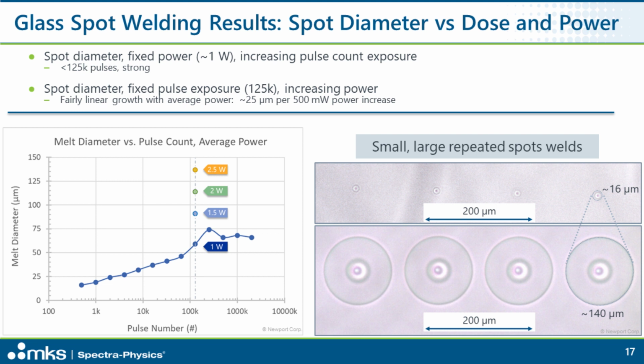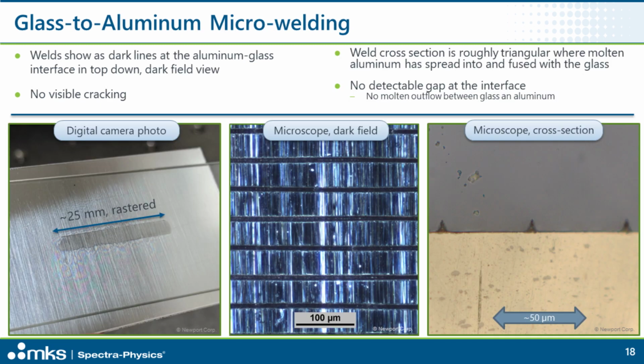So this precision of control is illustrated with the images at the right. We have the very smallest picture with the low pulse count of 16 micron melt width, and then contrast that to the very large melt size of roughly 140 microns, and each spot, whether it's a small spot or a large spot, is very repeatable, very smoothly symmetric about the center of the focus and the center of the energy input into the glass. So that's basically a wrap up for the glass type of welding experiments.